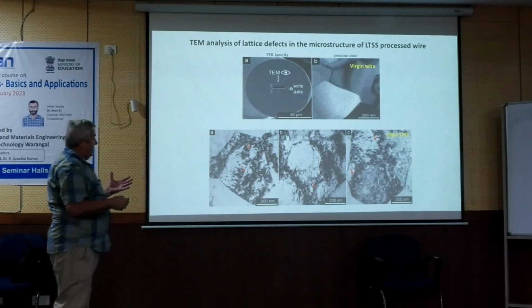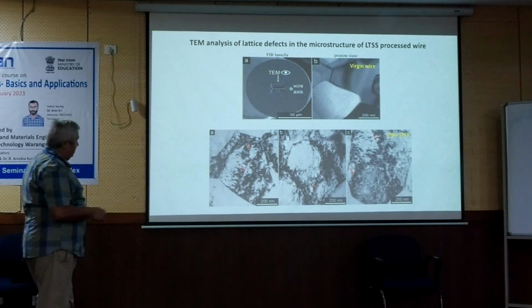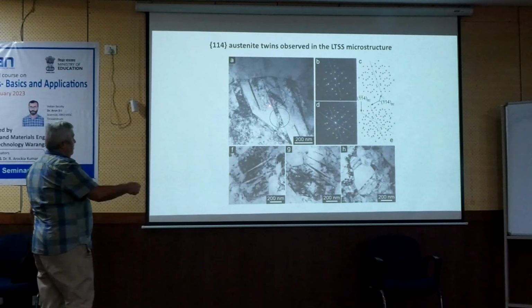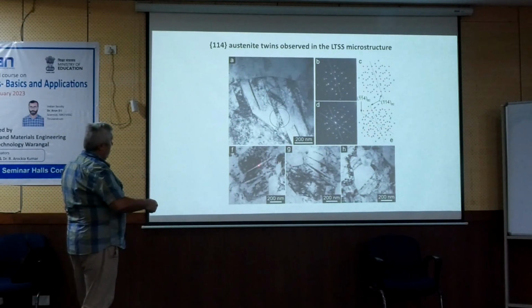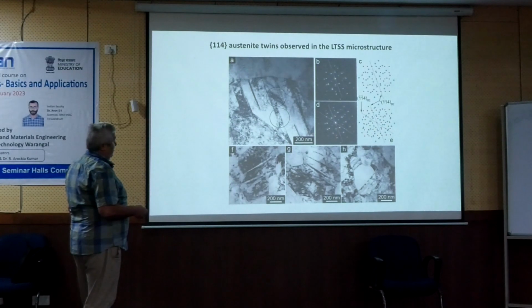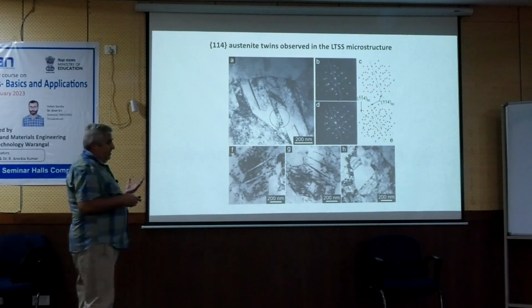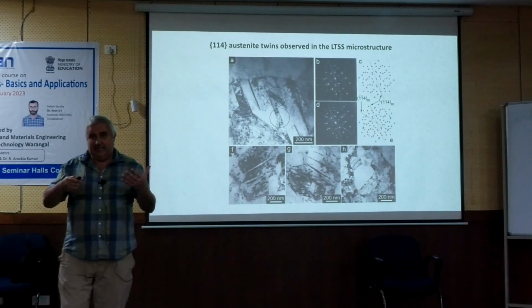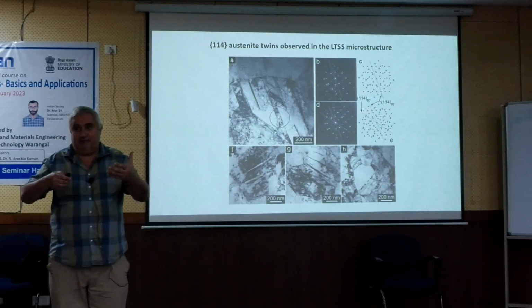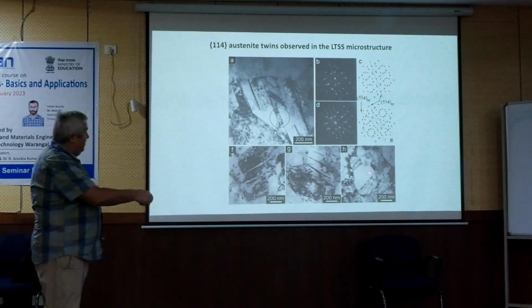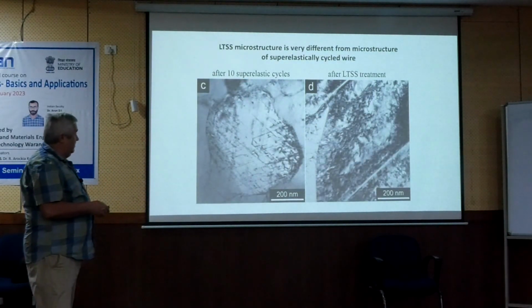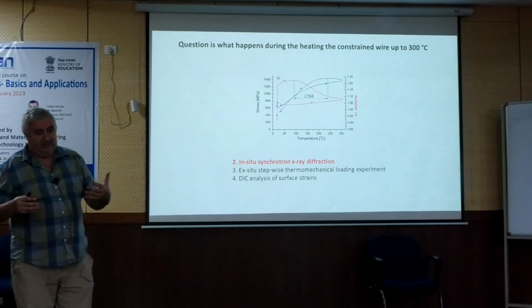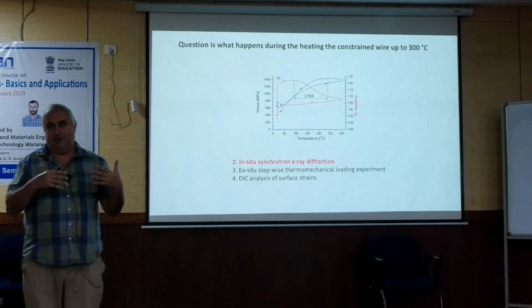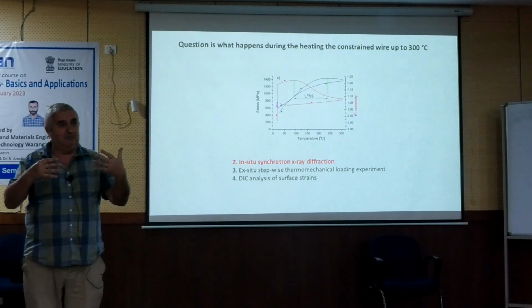Of course, we try to look into the microstructure. In the microstructure there are dislocations and deformation bands. So these are the deformation bands. This was published already about 10 years ago. They were first twins, austenite 114 twins, which we found in this microstructure. So we realized that the process which occurs in martensite creates these twins, and after unloading and cooling, we see them in austenite. So it was the first experimental evidence for this kinking or twinning, that we have found these twin bands, and so this process is important for the shape setting.